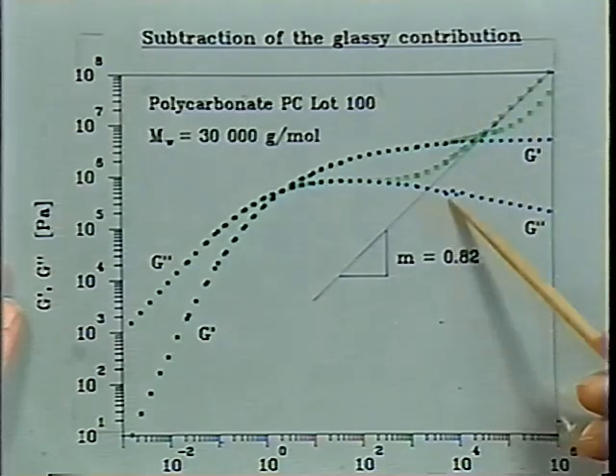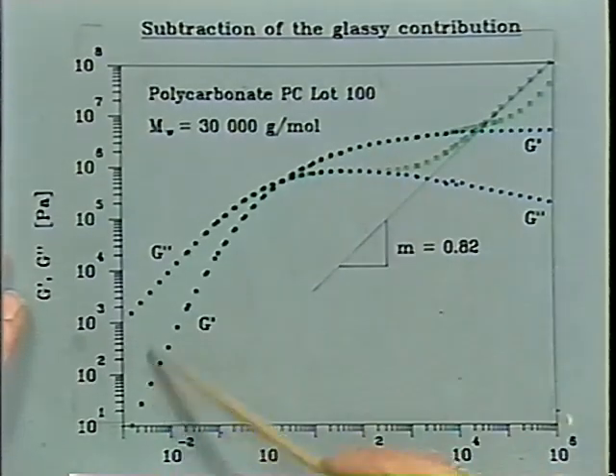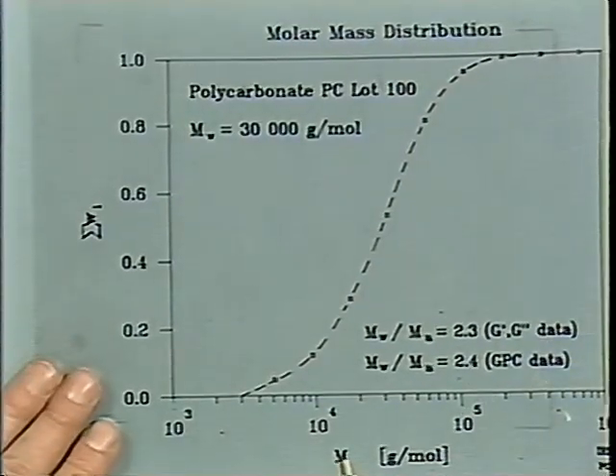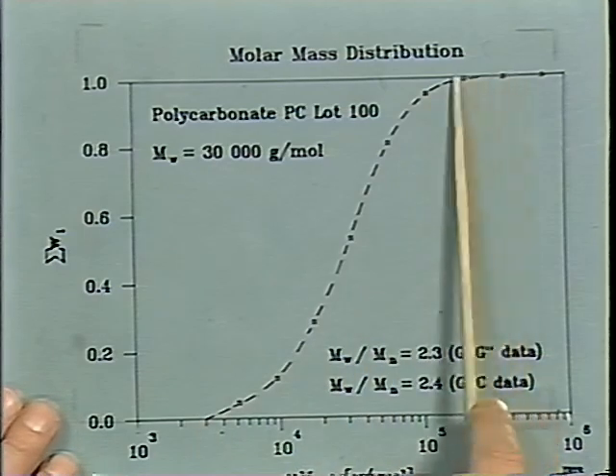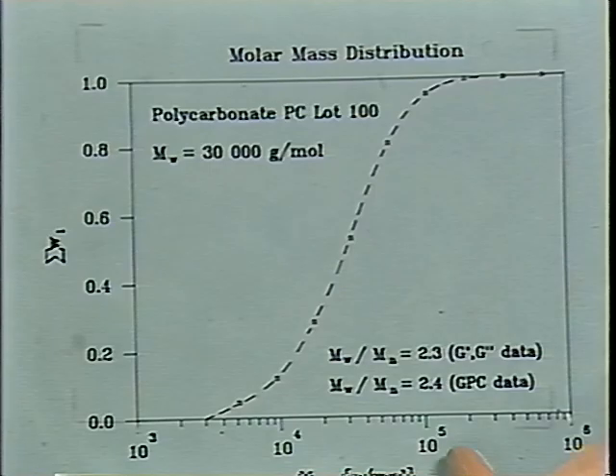Michael subtracted the glass transition behavior, so he has this curve, here the blue curve, and then he takes that spectrum and analyzes it in terms of a molecular weight distribution. This is the sum of the weight fraction as a function of molecular weight, and you can see how you go from 0 to the complete polymer, and you get the distribution of molecular weights in that fashion. And that looks reasonable, but I think we should analyze this in greater detail. But I hope you got the general idea of the approach, and maybe you have some ideas how to improve methods like that.